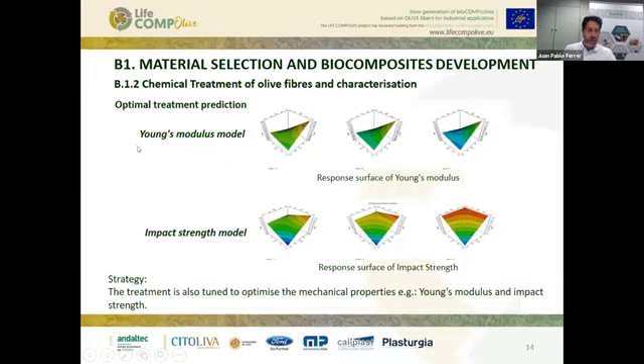For the optimum chemical treatment regarding the mechanical properties, we applied also another mathematical model. For example, for the Young's modulus, we obtain different response surfaces, as we see here on the top, and we also applied an equivalent mathematical model in order to optimize the impact strength. So this mathematical tool allowed us to fulfill the requirements of the industrial users.